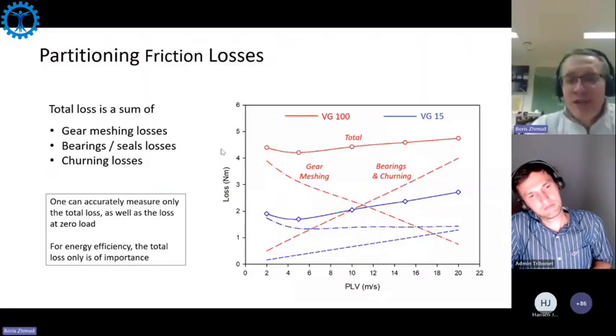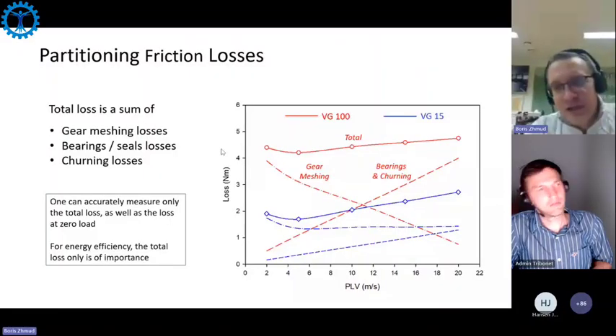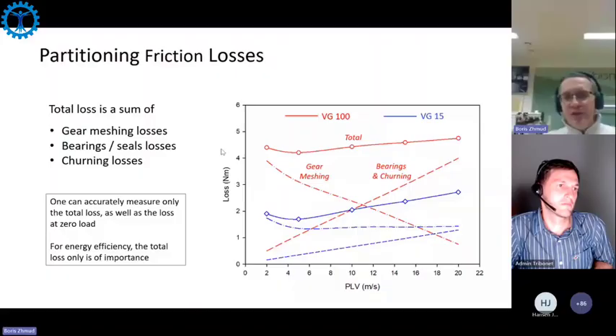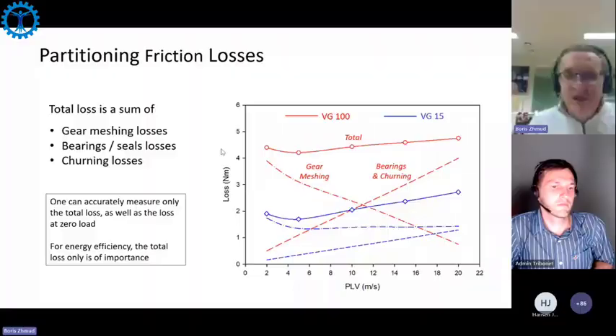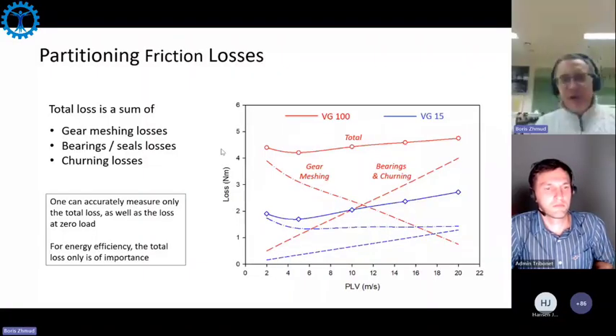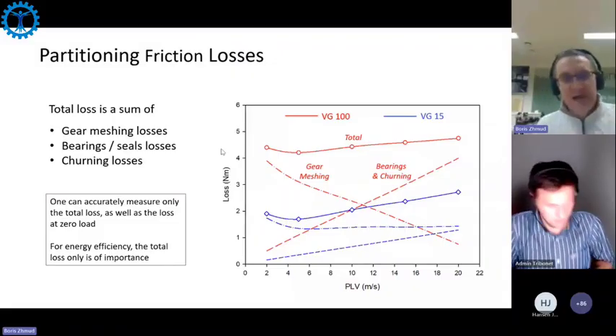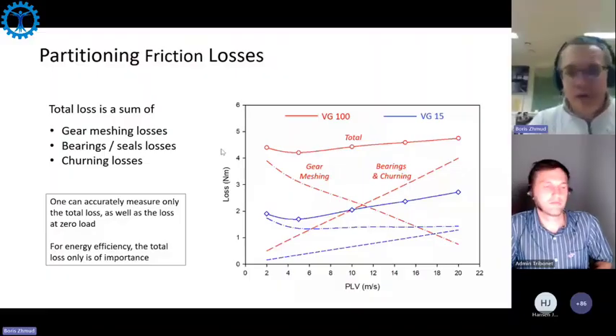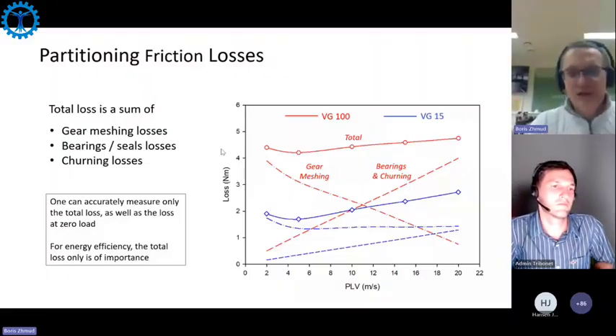And this really describes the challenge of electric transmission design. It would be extremely easy to get a very robust transmission if the gearbox would run at the same high speed. But unfortunately, it has to start at low speed and high load. And when you have low speed and high load, you need a high viscosity lubricant. But when you have high speed and low load, you would do better with a low viscosity lubricant. So you have to find some compromise which would adapt to both of those conflicting limits.